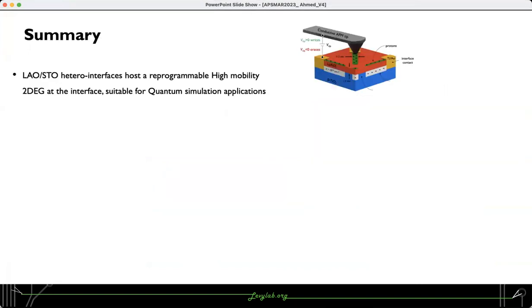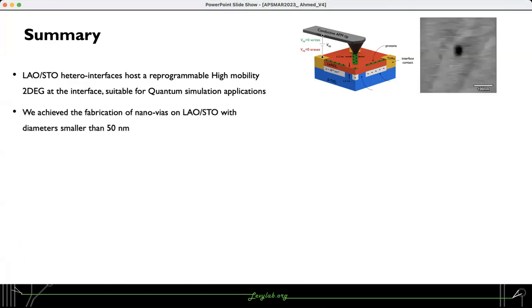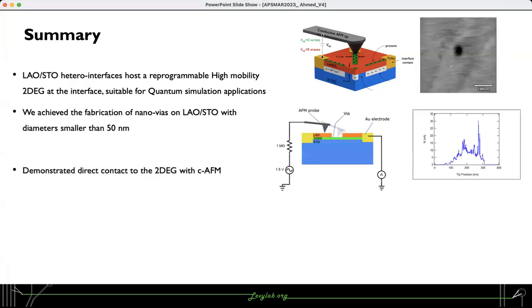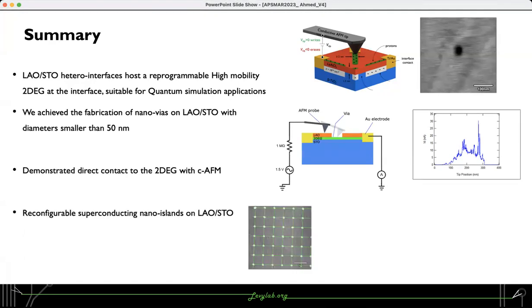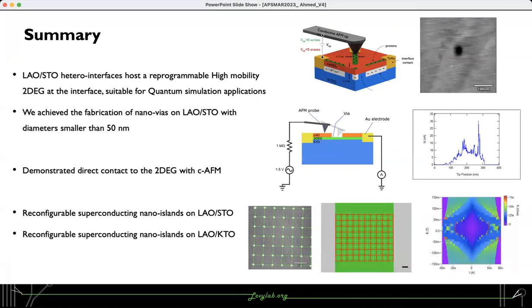To summarize, the LAO-STO heterointerface is a promising reconfigurable quantum nanoelectronics platform that is suitable for many quantum applications. Improved coupling to other quantum materials can be achieved by etching lanthanum aluminate in small windows. Direct contact to the 2D electron gas can be demonstrated using conductive AFM. We're interested in many applications of this method, including reconfigurable superconducting nanoislands on LAO-STO. Finally, we are interested in creating arrays of Josephson junctions in LAO-KTO and using them to probe questions about the nature of superconductivity in 2 dimensions.